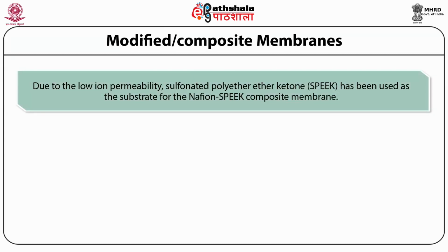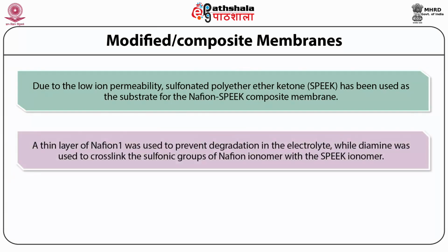Now, due to the low ionic permeability, sulfonated polyether ether ketone, that is SPEEK, has been used as the substrate for the Nafion SPEEK composite membrane. A thin layer of Nafion was used to prevent the degradation in the electrolyte, while diamine was used to cross-link the sulfonic groups of Nafion ionomer with the SPEEK ionomer.